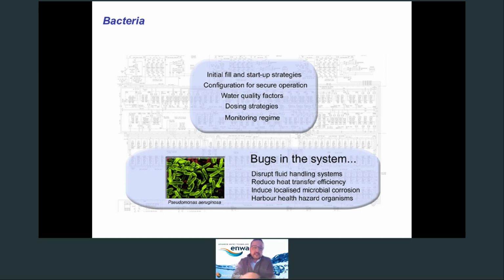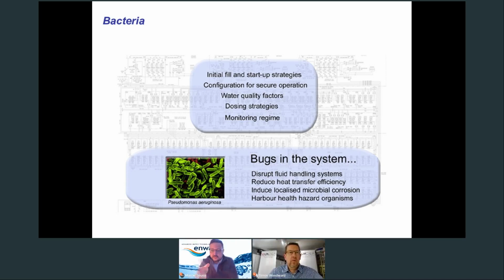And in the case of bacteria, bacteria can exist on almost all systems. This is the nature of microorganisms. And given the right conditions, they can survive and thrive. So without adequate filtration and water treatment, biofilm begins to form when bacteria adhere to surfaces in water environments and begin to excrete a substance that can attach itself to a variety of materials, including metals and plastics. As biofilm grows in the systems, it becomes nutrients for bacteria, which helps them develop and progressively become more difficult to control. The impact on the system is an insulating layer, which can be greater than scale, causes blockages, and can cause microbiologically influenced corrosion, gas production, and the local deterioration of the pipework.